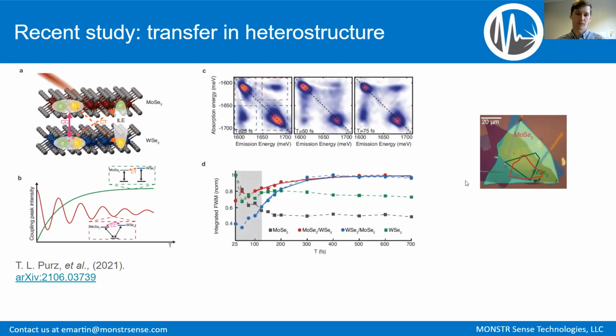So basically, you correlate the absorption and emission energies using 2D spectroscopy. And then what they did is they looked at those coupling peaks. So that's where you have absorption at one energy, emission at another energy. And they looked at how that evolved with the wait time, right?